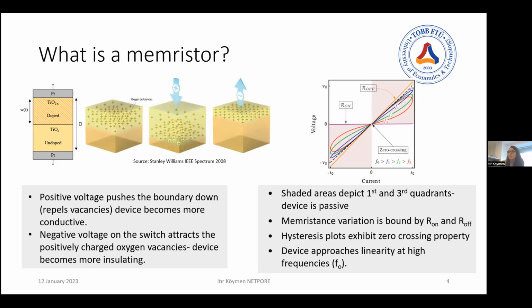And once that's removed and negative voltage is applied, the oxygen vacancies, positively charged vacancies, are drawn towards the top electrode where the voltage is applied, and the device becomes more insulating. So the effect of this is shown here. This plot is counterintuitively for a current input, so the x-axis is current, but the effect doesn't change. So what happens is when oxygen vacancies move, the device might start from the more conductive state, so this one. And after a certain point, due to the input, this device will switch to a more resistive state.